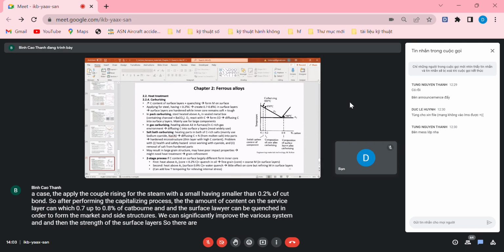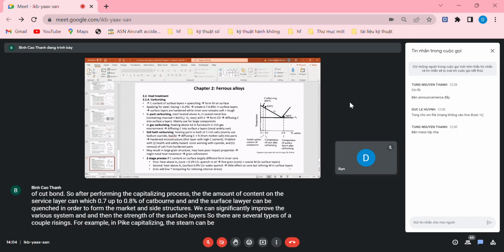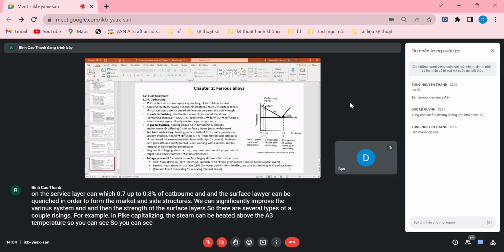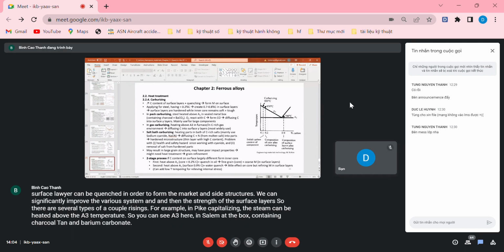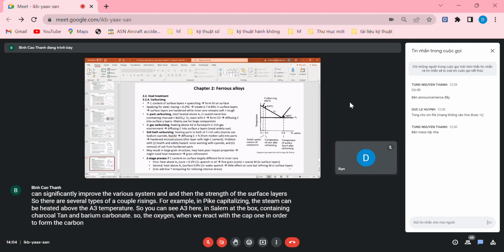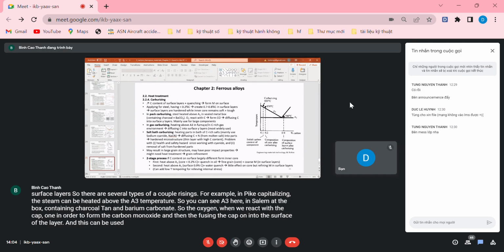There are several types of carburizing. For example, in pack carburizing, the steel can be heated above the A3 temperature. You can see A3 here. In a metal box containing charcoal and barium carbonate, the oxygen reacts with the carbon to form carbon monoxide, and then the carbon diffuses into the surface austenite layer. This can be used for enhancing the carbon content on the surface layer of large components.